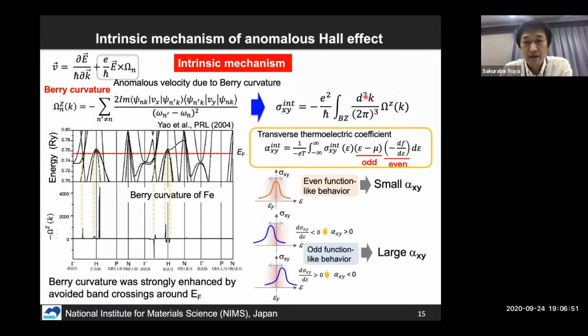And if we can calculate it, sigma xy, alpha xy, the off-diagonal part of the thermoelectric tensor, can be calculated by this Mott equation. Here, E minus mu is an odd function around the chemical potential, and this energy derivative of the Fermi distribution function is an even function around the chemical potential. So the energy dependence of sigma xy determines the magnitude of alpha xy. Namely, if sigma xy shows this kind of even function-like behavior, alpha xy must be small.